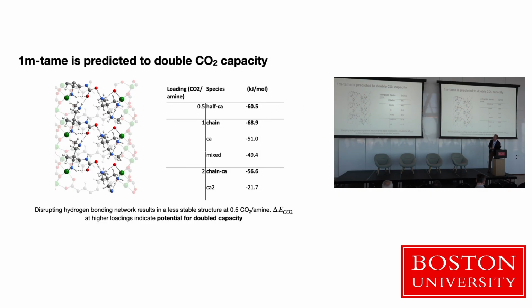One of the things notable is the predicted energies of binding are roughly the same, and that suggests the structure will potentially absorb as much as that. That hasn't been confirmed yet, but I wanted to leave you with this structure in that this is a very hard structure to get with energy minimization, and it was a lot of simulated annealing plus this MLIP that allowed us to predict this structure.